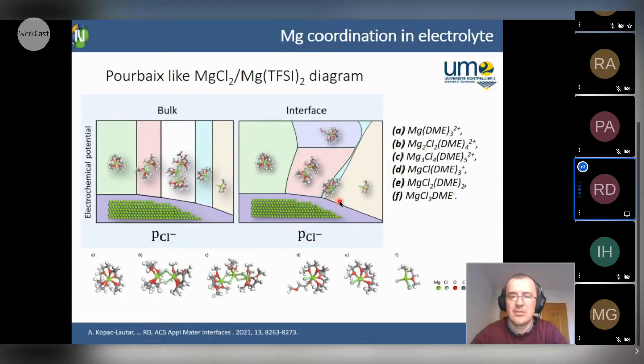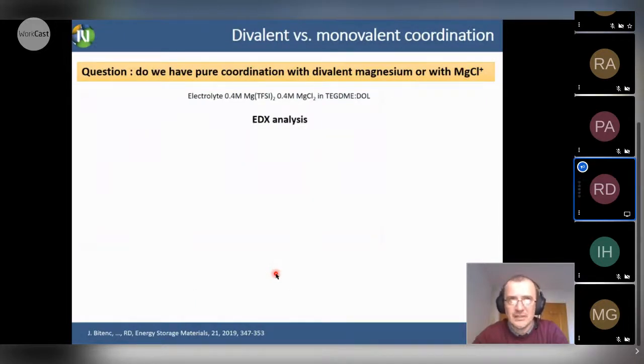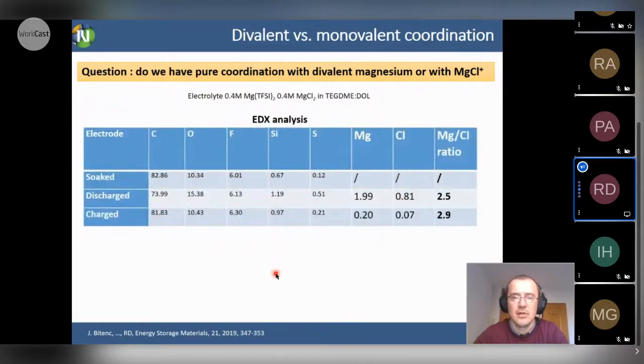Then this distribution of species is completely different than in the bulk, and this part of development is still unclear, and still needs a lot of experimental proofs and also computational calculations to understand a little bit better what is happening on the interface. But as we know that magnesium in chloride solution can also be monovalent magnesium chloride, we went in carefully, we inspected electrodes, and